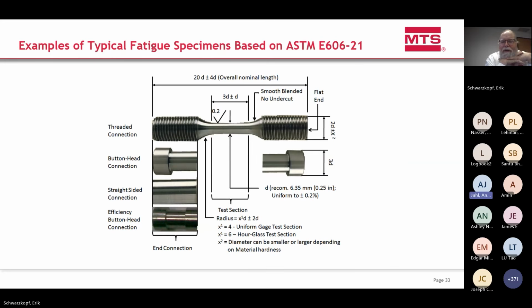ASTM E606 is the strain-controlled low-cycle fatigue standard used by ASTM, and there's an equivalent standard for ISO. Because these specimens usually go through zero, having both tension and compressive loads, we need different kinds of gripping than we might use for a tension stress control test or a tensile test in general. The loading needs to go through zero without any slop or any kind of mismeasurement.